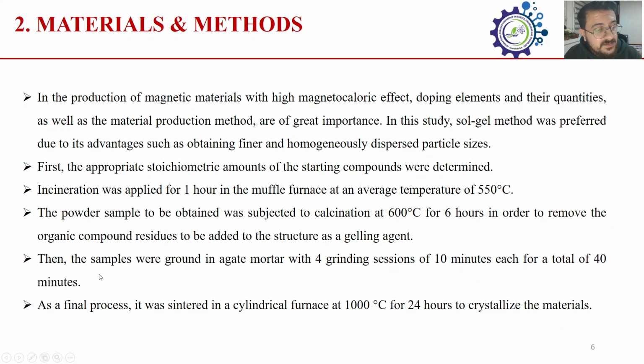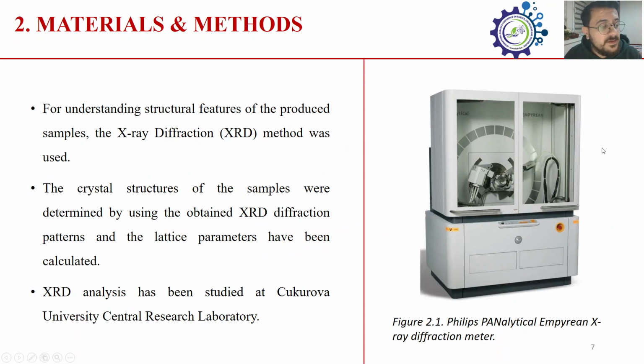Then the samples were ground in an agate mortar with 4 grinding sessions of 10 minutes each, for a total of 40 minutes. As a final process, it was sintered in the cylindrical furnace at 1000 centigrade degrees for 24 hours to crystallize the materials.